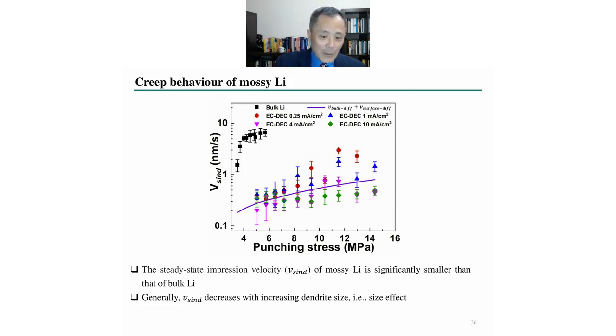The reason for this is that during electroplating, there is this solid electrolyte interface, an inorganic layer formed on the surface, on the internal surface of the pores. The inorganic material is stiffer and does not deform, does not creep. Therefore, the mossy lithium is more creep resistant than the fresh lithium foil.